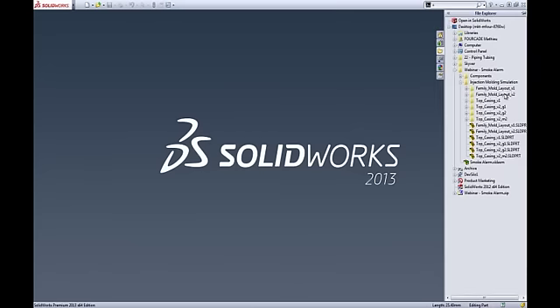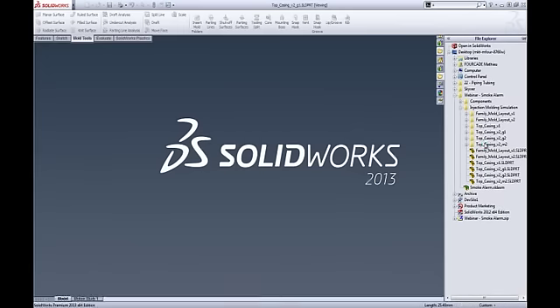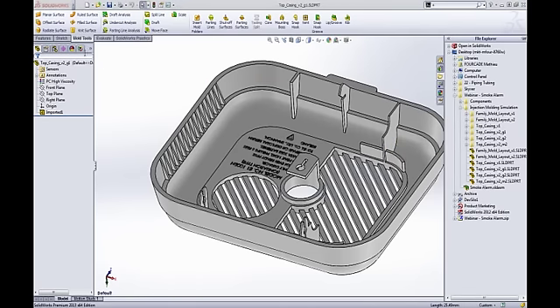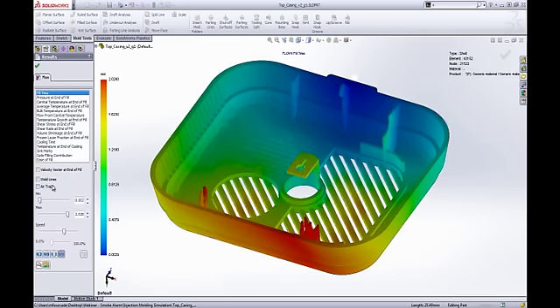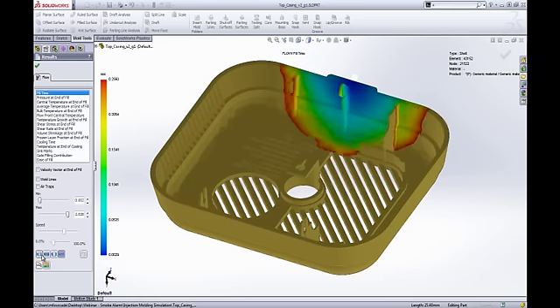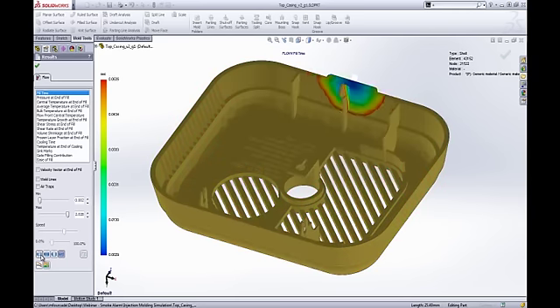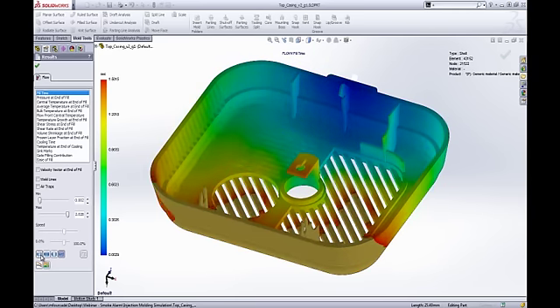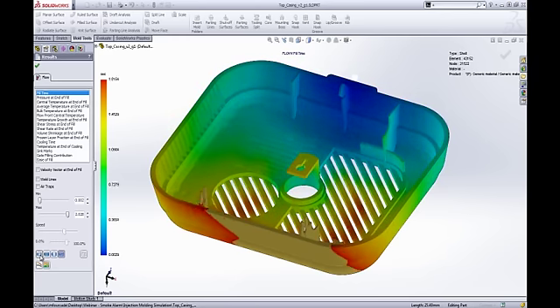For the second example, we're switching to another design iteration. You can try so many different scenarios so fast. In this case, we simply redefined the geometry a bit — with slightly thicker ribs so that plastic flows better, and a more uniform thickness everywhere, so the racetrack effect is more limited. But we still have weld lines almost at the middle of these long thin ribs. We know it's a weak point of the part, so we definitely want to avoid back-filling here.